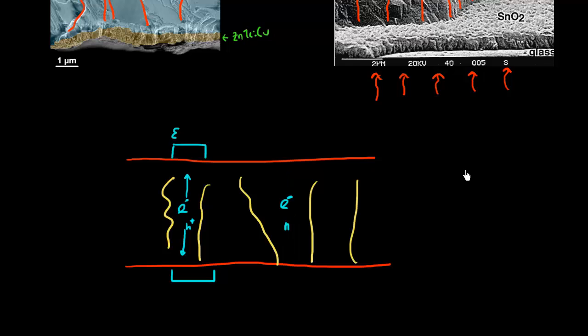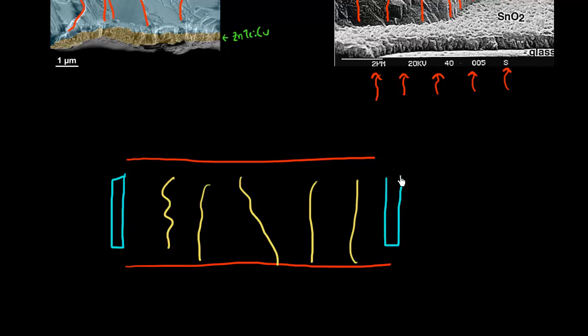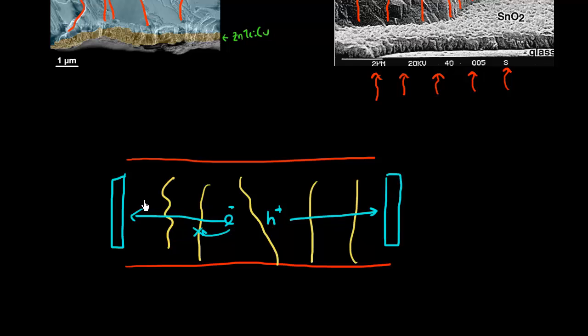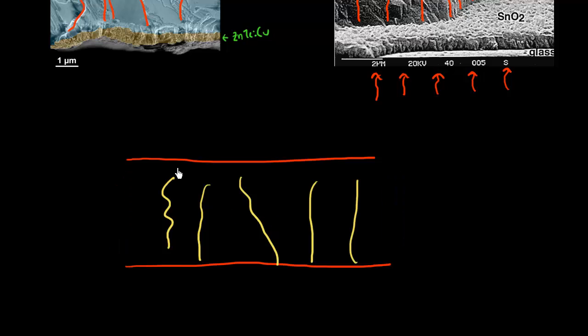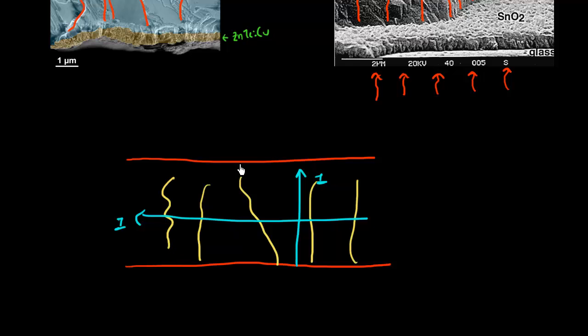Versus if my cell was of such a kind that I had my n-type and p-type contacts placed such that I was collecting electrons and holes along a direction perpendicular to the grain boundaries, there would be a very large chance that an electron might recombine as it traverses through a grain boundary. Even if it missed one grain boundary, it would soon encounter another, and it is very likely to recombine before being collected. So grain boundaries are still a major concern, but they would be an even bigger concern if the current flow direction were perpendicular. Since the current flow is parallel to the grain boundaries, it helps alleviate some of their impact.